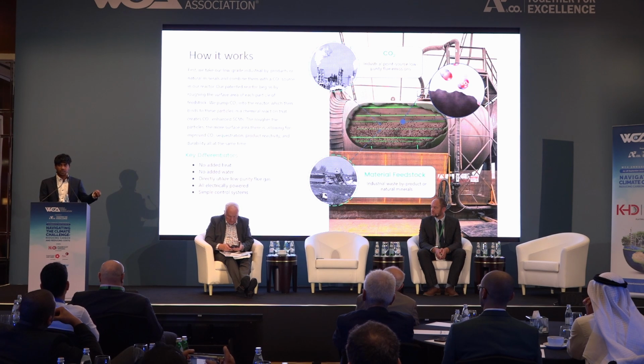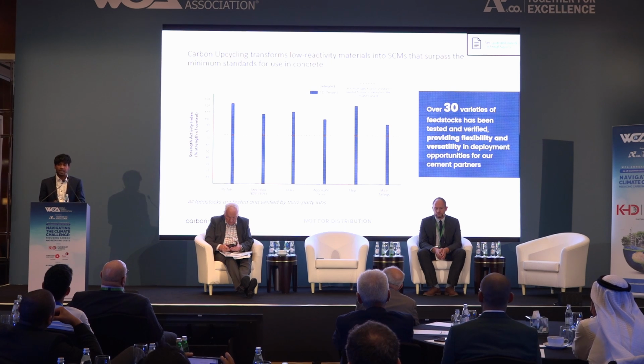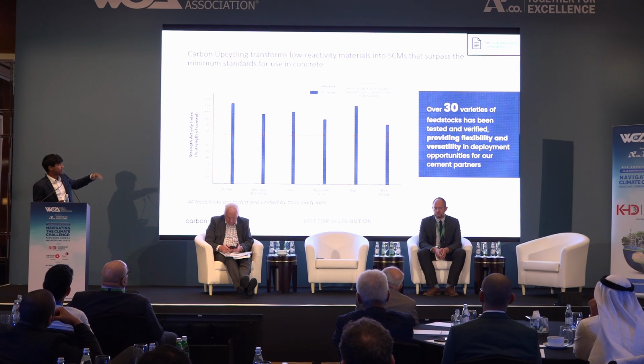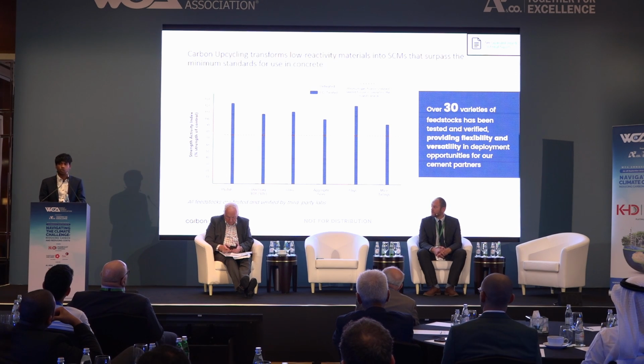So instead of just sequestering the CO2 and making something inert like an aggregate or a sand, we have actually shown that we can significantly improve the baseline performance of that SCM. We've taken some raw clays, we've taken crushed glass, we've taken steel slags, and of course, things like fly ash and mine tailings that have been talked about a little bit this morning. And what we've shown is that we can get them well above that 75% threshold in terms of strength activity, which is the baseline table stakes for people to look at pozzolanic additions on site.